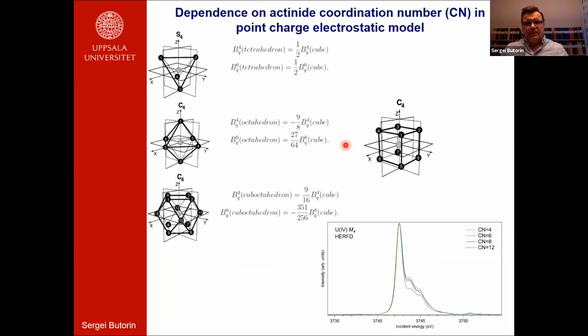Now I move to the dependence of this HERFD spectrum on the actinide coordination number. It's actually a question how sensitive these HERFD spectra can be to changes in the actinide coordination number. But it's not easy to study this point experimentally, because between different compounds there is a difference not only in the actinide coordination number, but also in the actinide-ligand distance and the charge on the ligand. But it's easy to do in calculations.